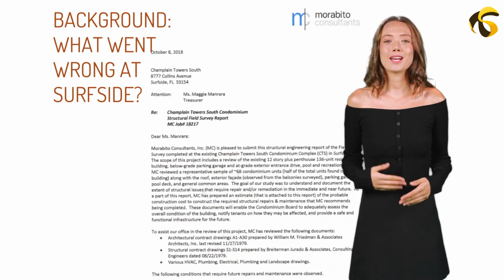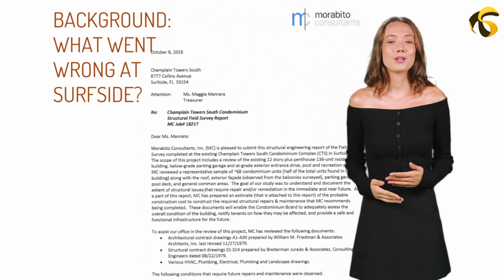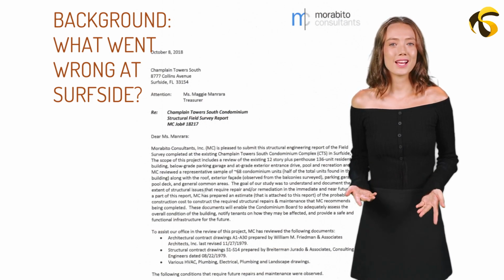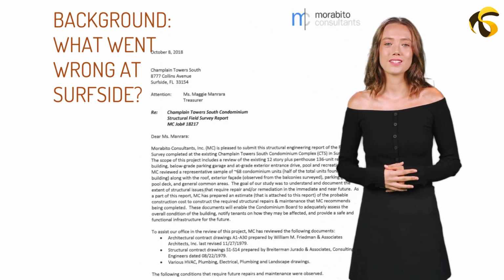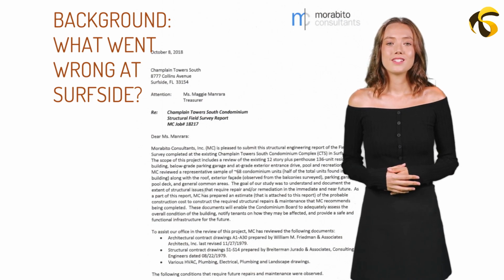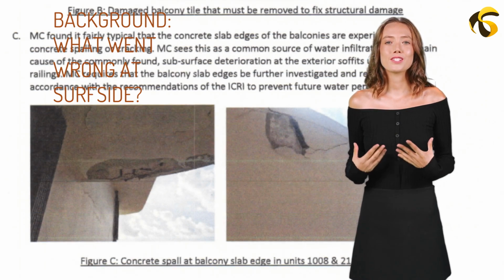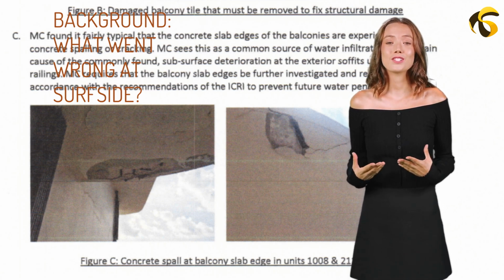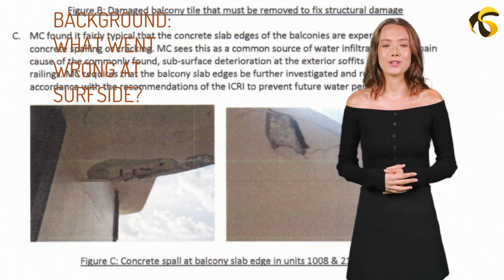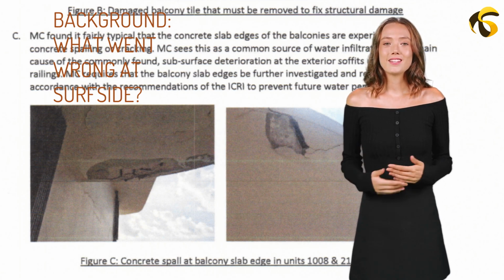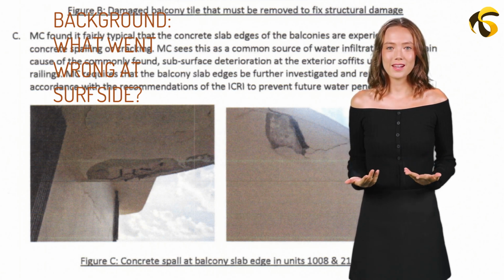Crucially, the report identified the cause. Failed waterproofing on the pool deck and planters had allowed water to seep into the concrete slab and attack the reinforcing steel. In a letter to residents, the condo board warned that large sections of the pool deck had no effective waterproofing, leaving the garage ceiling and structural slab exposed to water intrusion for 40 years. Even where a waterproofing membrane existed, it had deteriorated past its service life, allowing water to get underneath and cause